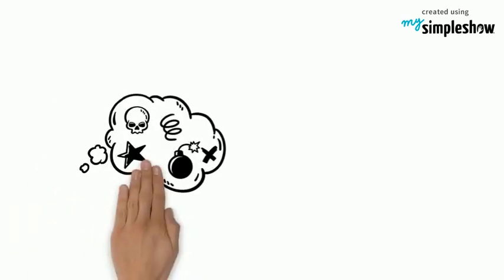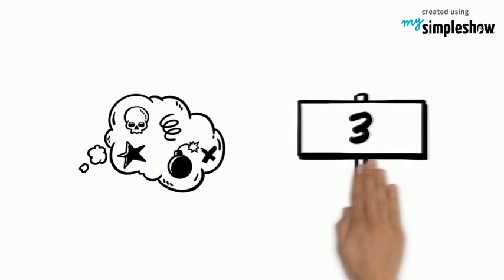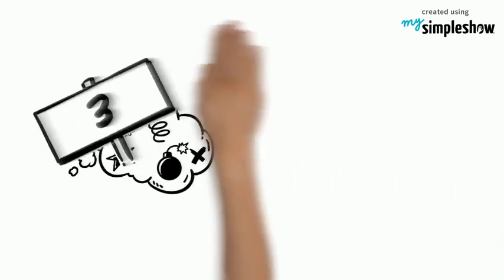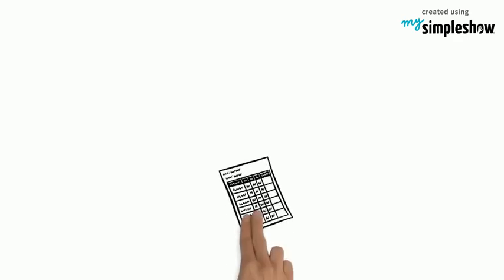Microstructure examination. Typical microstructure of the submitted shaft, tempered martensite, Nital 3% etch. Fractographic analysis. Examination of the available fracture surfaces was performed at macro scale.